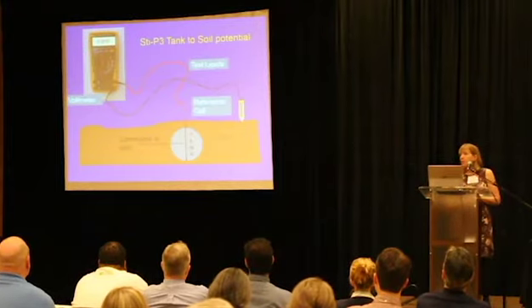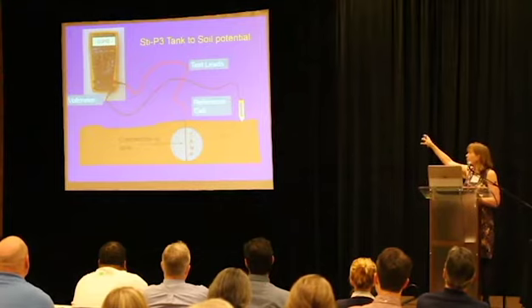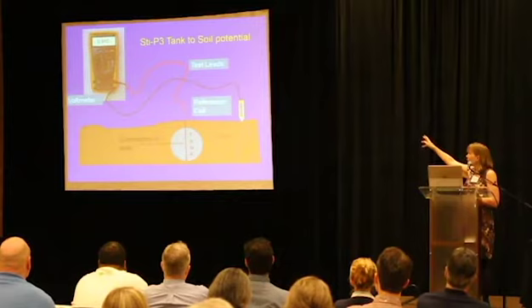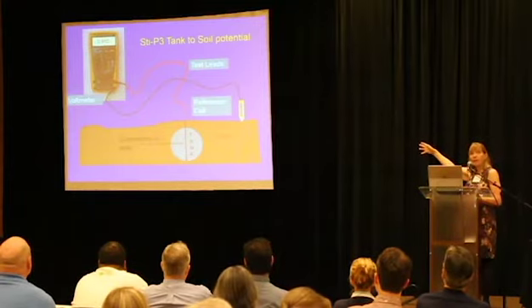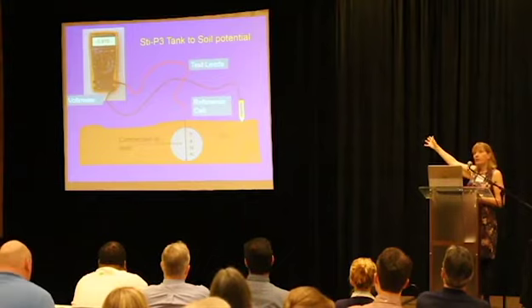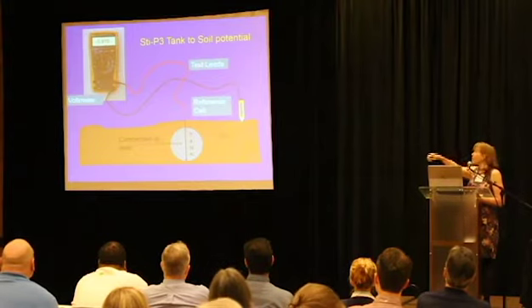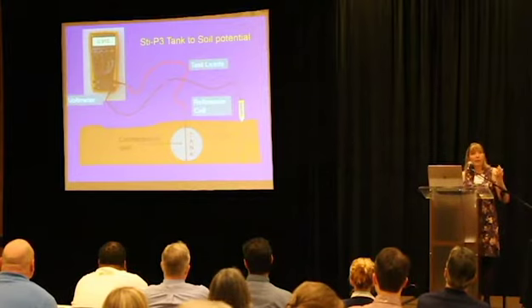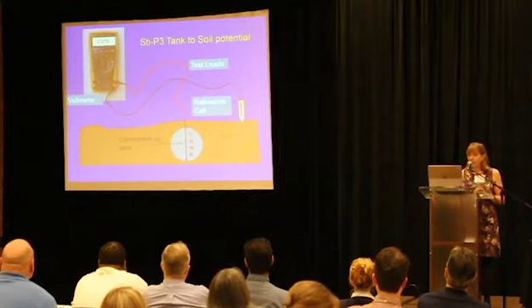So we tell all the testers the very first reading that they're going to take on a sacrificial system, if they're testing an STI-P3 tank, is a remote reading. It's going to be at least 30 feet out, and we're going to talk a little bit more about that. But at least 30 feet out away from the tank. Use that as your first reading, and it'll give you a very quick, good idea of how well that system is operating.